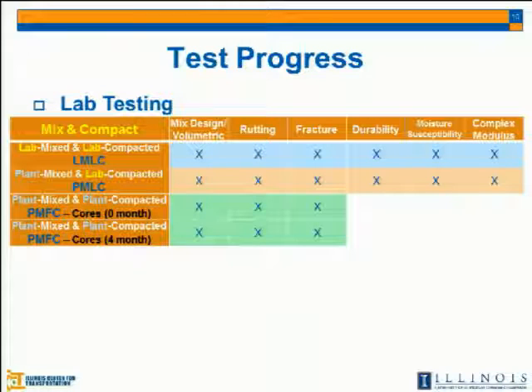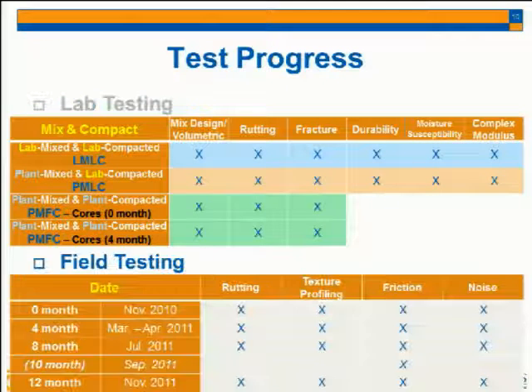So here is the matrix for lab mixed and lab compacted mix, and then plant mixed and lab compacted mix. We did the 5 performance tests, and also we took the cores right after construction and then 4 months after construction. But because of the core size, we only conduct the rutting test and fracture test in the lab.